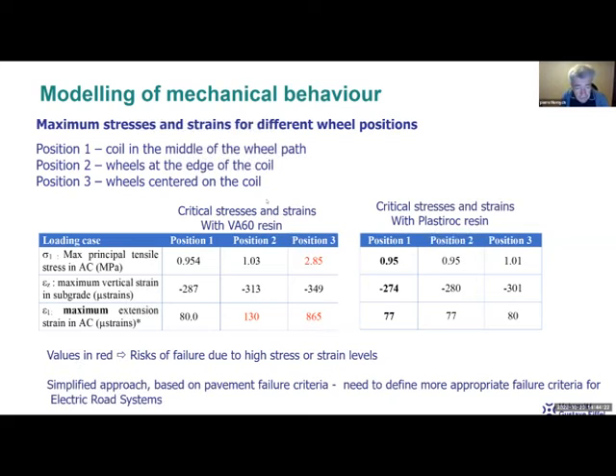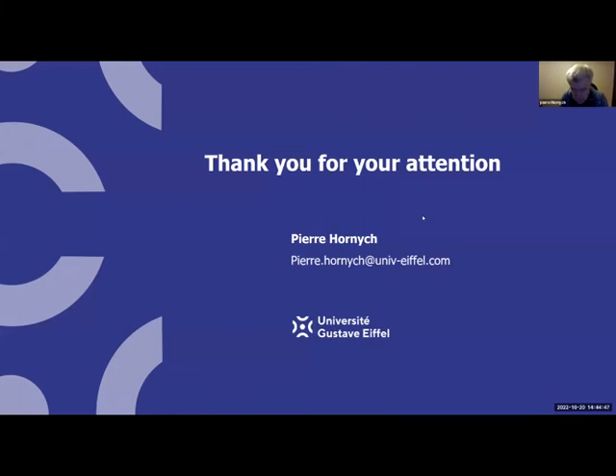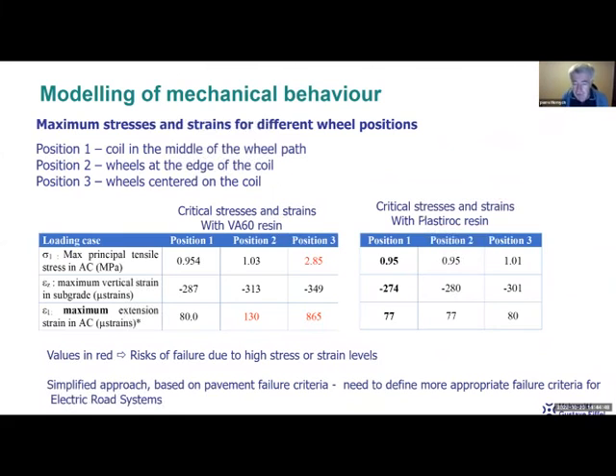And we did these calculations with different materials for the coil, and especially for the resin, which is around the coil, which is sealing the coil in the pavement. And here you can see the difference of results between a calculation with the resin called the VA60, which is a very soft resin, and another resin, which is called Plastiroc, which is a stiffer resin and which has a modulus very close to the asphalt material.